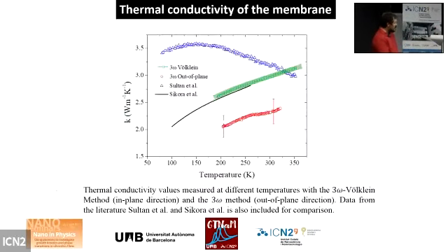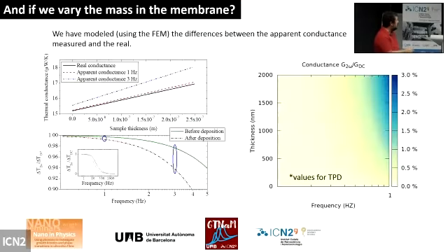As we increase the sample mass after and before the deposition, here is the 10%, the ratio between T 2 omega and T DC. If we are at frequencies of 1 Hertz or below, the mismatch between the two variables that we want to measure is very low.